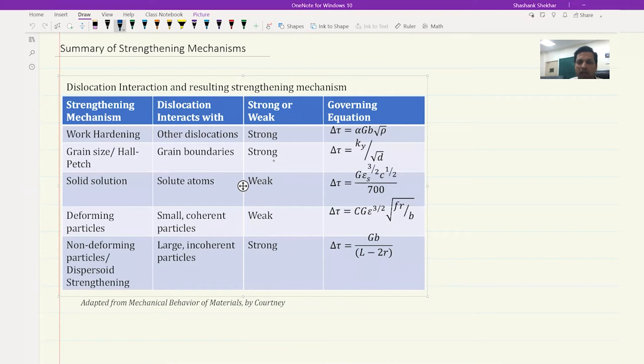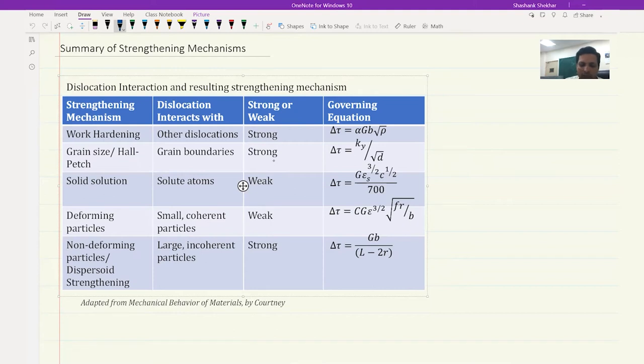This column tells you which dislocation interacts with which particular entity, which results in the strengthening of the material. Strengthening happens because in the end, dislocation is interacting with some entity. In the case of work hardening or strain hardening, dislocation is interacting with other dislocations, and it is overall a strong strengthening process. The relation is given by the Taylor relation: alpha times G times b times root rho. Then there is also the grain size effect or the Hall-Petch relation, where the dislocations interact with the grain boundaries - again a very strong effect. The increment in strength is given by ky divided by root d, where d is the grain size and ky is a proportionality constant. Then you have the solid solution, where the dislocations interact with the solute atoms - the overall effect is kind of weak.